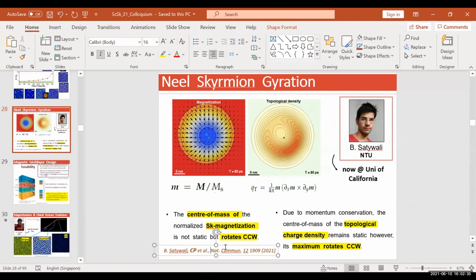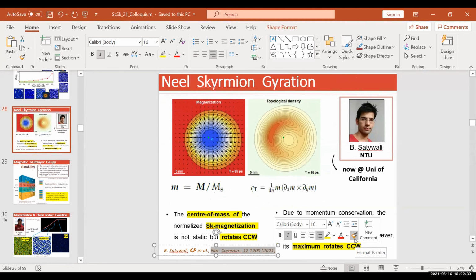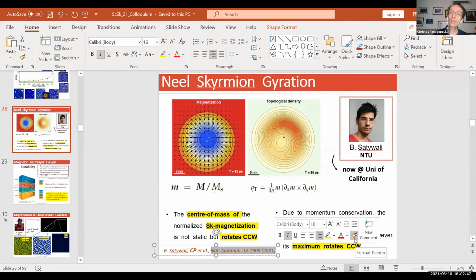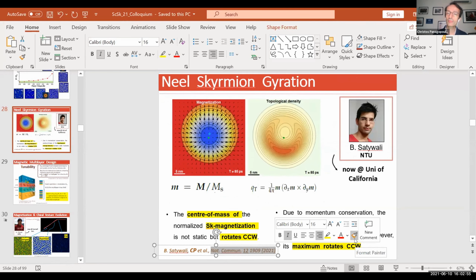Oh, okay. So how is the reliability of the ferromagnetic resonance to detect skyrmion phase? I mean, if we are not looking for other direct technique like magnetic force microscopy, can we rely only on FMR? No, we do a combinatorial method. And in fact, this article in Nature Communications is the first ever ferromagnetic resonance in multilayers hosting chiral textures and skyrmions. And what we show there is that ferromagnetic resonance measurements, either as a function of field or as a function of frequency, coupled with analytical theory and micromagnetic simulations, can actually identify the details of the different textures across a wide frequency range in a complex multilayer system. And also it can identify not only the magnitudes, but also spatial orientations.